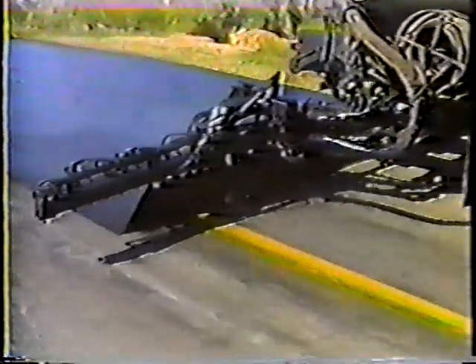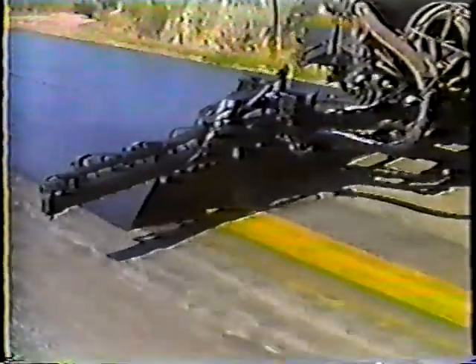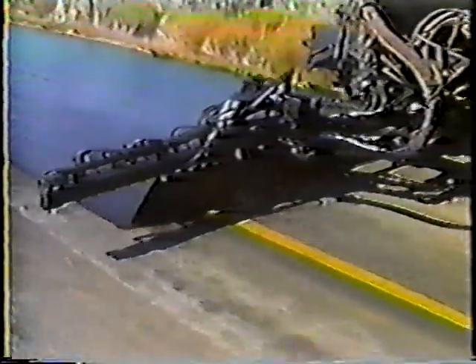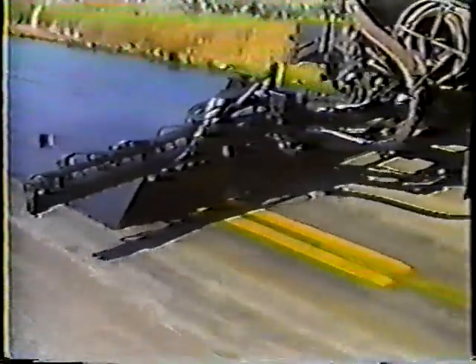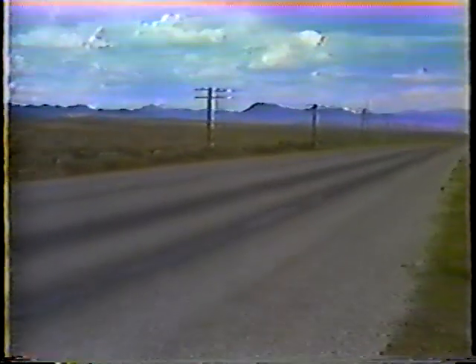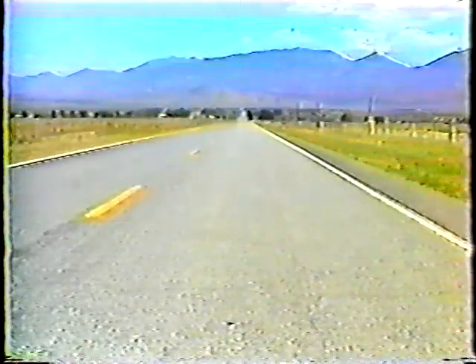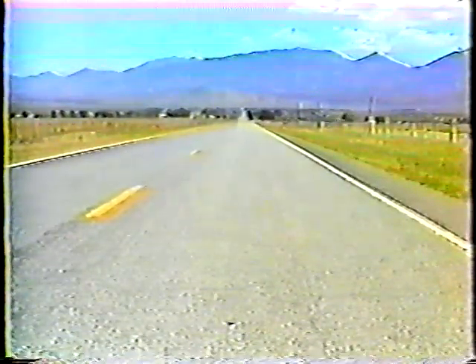The amount of liquid asphalt that's applied over a given area is referred to as the application rate. And getting the right application rate is one of the most critical parts of the whole job. If there's too much, it'll bleed through the cover material and start tracking and rolling the chips. And if there's too little, the liquid asphalt can't hold the cover material in place. But the right application rate will hold the cover material in place without bleeding through the surface. Ideally, about 3/4 of each stone should be embedded in the liquid asphalt.